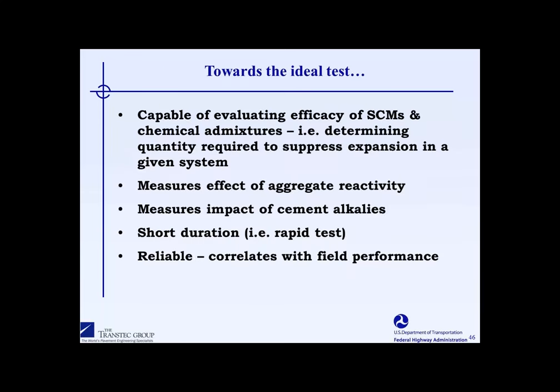So just in the last few minutes here, I just want to talk about this movement towards the ideal test. And again, as I said in the first slide, we're not anywhere near there yet. A lot of researchers are working on it. I think we have a reasonable suite of tests right now that, when used judiciously, can give the right answer in terms of aggregate reactivity, and also can estimate the amount of SCMs or lithium that's needed. But we don't have a test that can actually test the job mix.